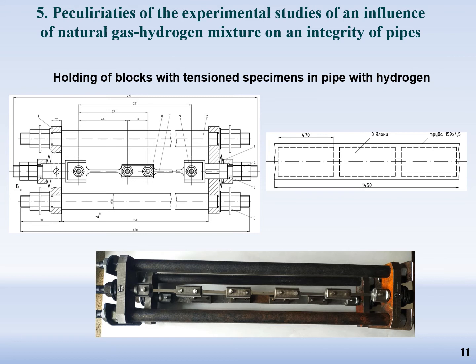The next peculiarity is as follows. A holding of specimens in pipe with gas-hydrogen mixture under preliminarily controlled tension with fixation of stress state. Here you can see the device for such a procedure, which enables to tension some specimens and gather them in the special block for placing inside the pipe for holding for a certain time, in months and years. It is predicted that thin specimens during such long-term time will be noticeably hydrogenated if such internal in-pipe environment can hydrogenate in principle.